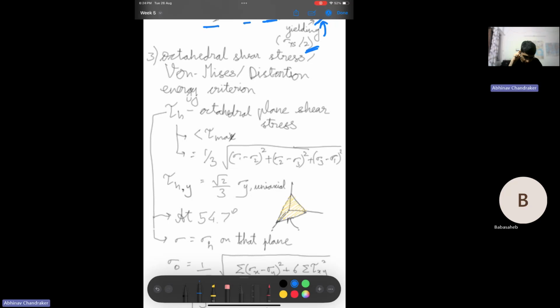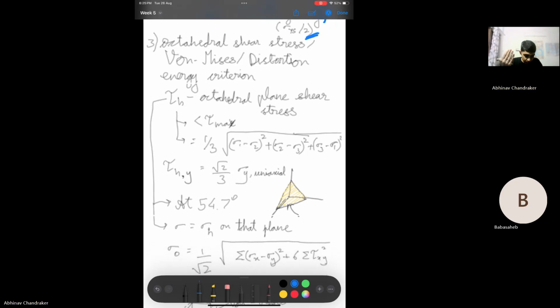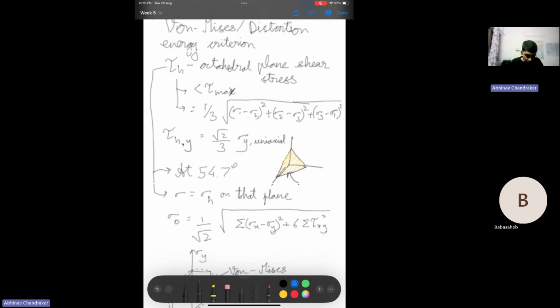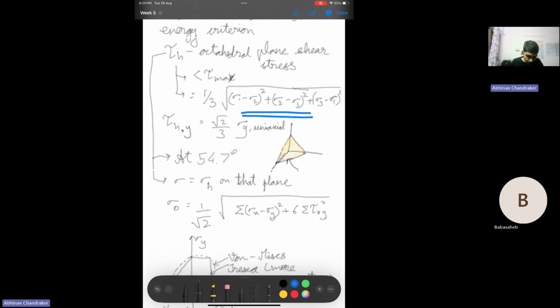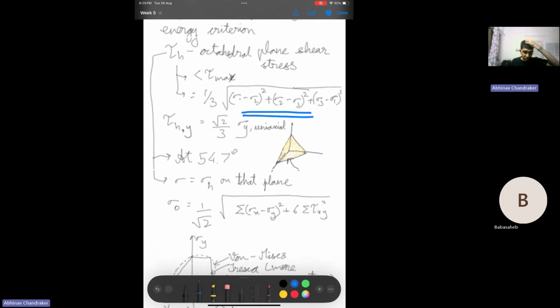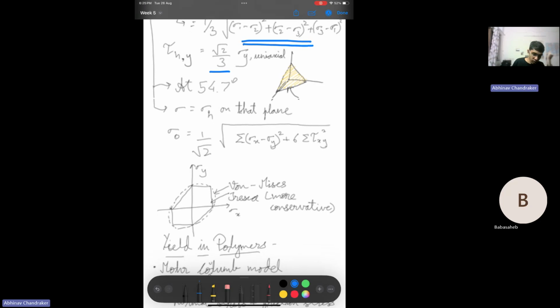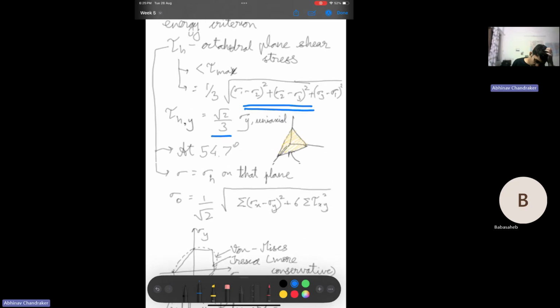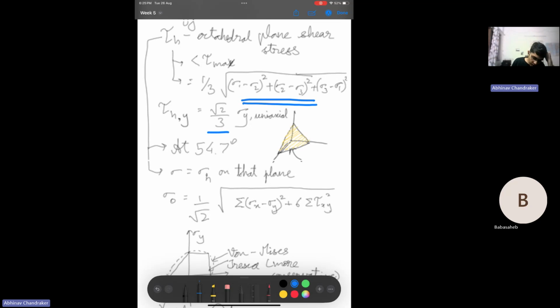So another criteria is the octahedral shear stress or von Mises or distortion energy criteria, where instead of looking at the stresses on the xy, xz, yz plane, you look at the stresses on the octahedral plane, specifically the maximum shear stress on that plane, and it will come out to have this value where sigma 1, sigma 2, sigma 3 are the principal stresses, and this should be more than root 2 by 3 into sigma y uniaxial, the counterpart for the uniaxial case. And this also happens to be the condition where you have sigma equal to sigma h. So on the octahedral plane, you will have the normal stress equal to hydrostatic stress.